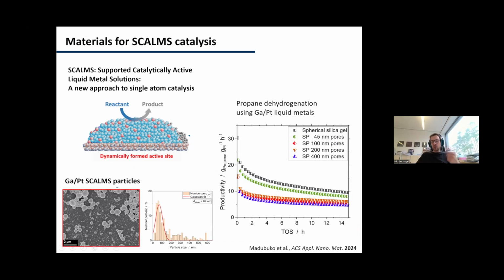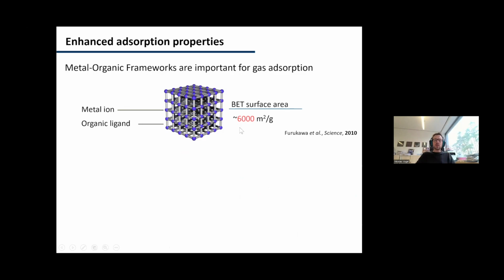stability over time. And that's exactly what we see here for just an example of propane dehydrogenation. And what you see here is that the productivity of the particles firstly depends on the amount of material that gives the overall height here, but more importantly, the gradient, so how quickly it runs into a steady state and whether or not it decreases, is very different for our superparticles, which are these colors here at the bottom, as compared to conventional catalyst supports. And that shows you that really we trap the particles in their native state and then can create a higher long-term stability.